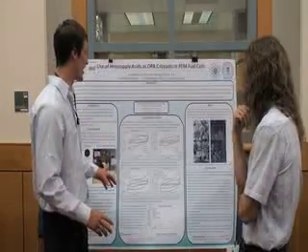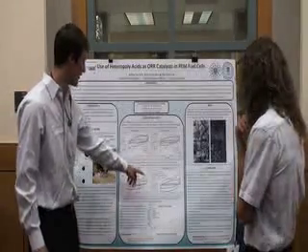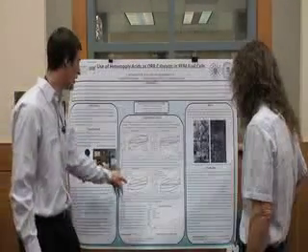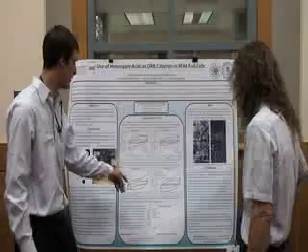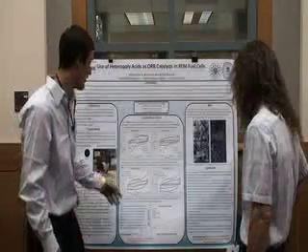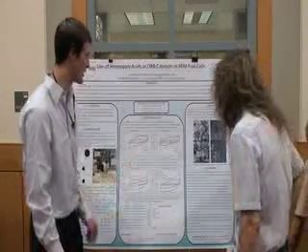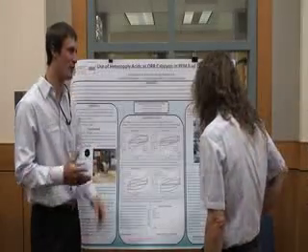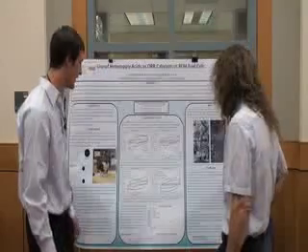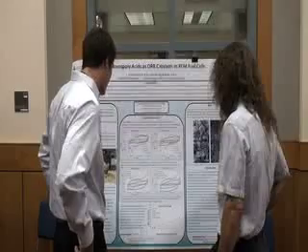So that's not a big shocker, but the interesting thing that happened was, down here, the black is just platinum on Ketjen carbon, and the red is just PMo11 on Ketjen, and then the blue is PMo11 and platinum on carbon. So it's a combination of the two. There's actually a decrease in capacity as well as a decrease in oxidation reduction activity of the catalyst. So if I were to just look at that, why would I not think that the platinum was the best? Well, it is.